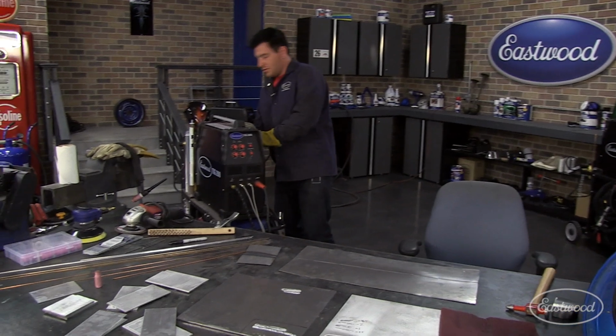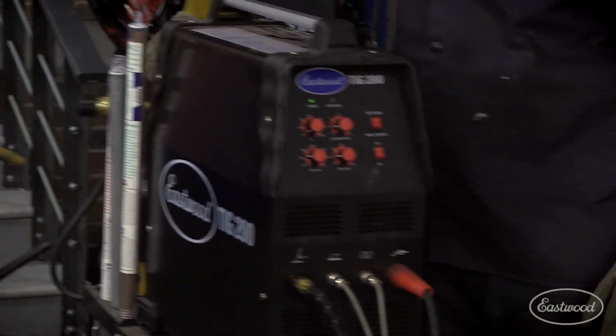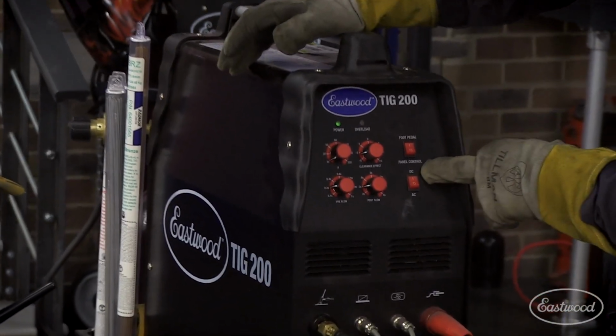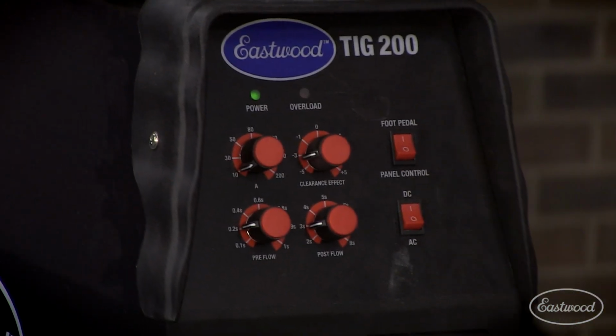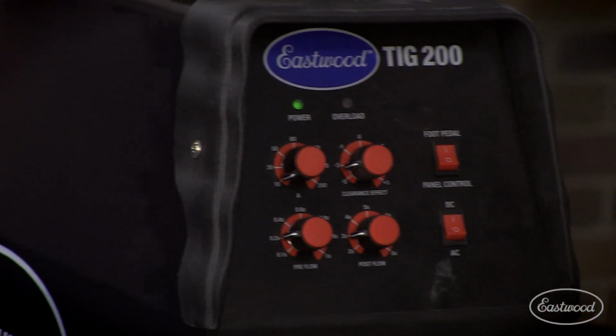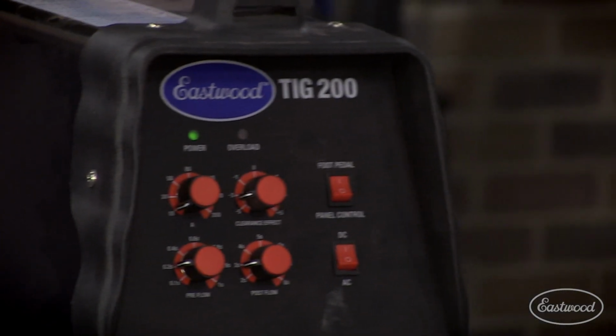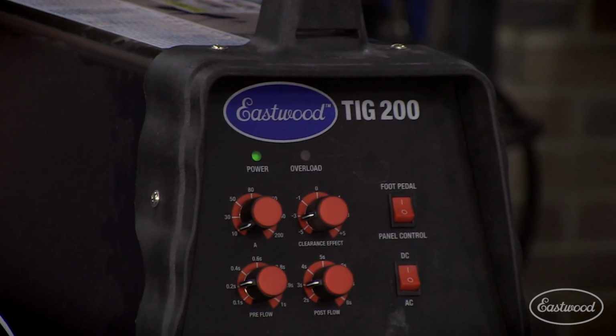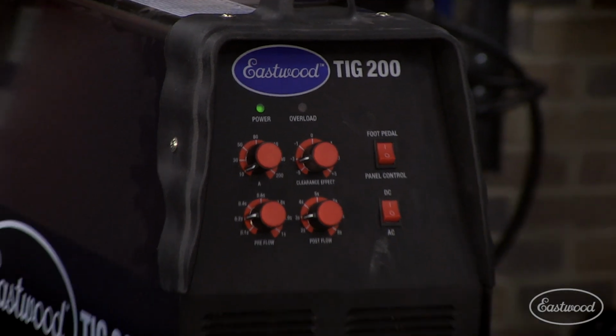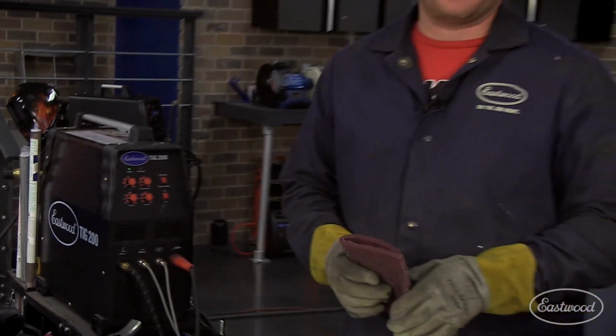So of course, got the TIG 200 like I said. Our gas is turned on. We're on DC here, and I'm going to adjust the amperage on the foot pedal. When you're welding sheet metal, you're going to keep it low amperage. Depending on the type of welder you have, you may max out at 80 amps, and you can work in that range from 0 to 80. You're probably going to be more in the 50 amp area or somewhere in there, depending how you like the weld. Maybe a little less, maybe a little more.